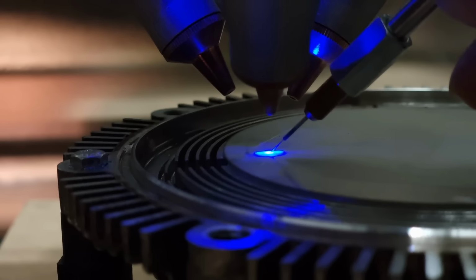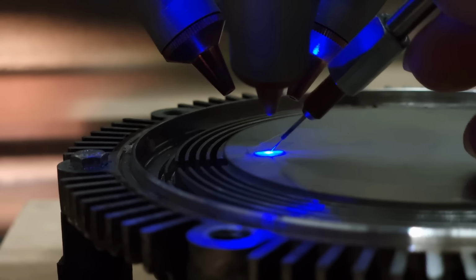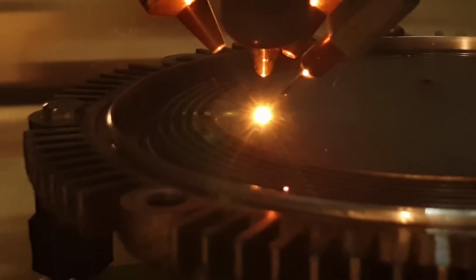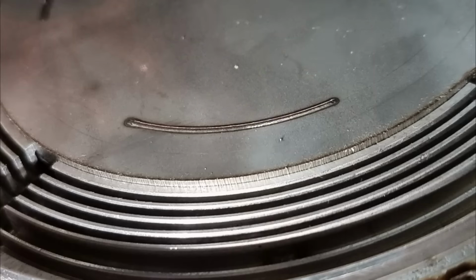Since I now had a rotating platform, I couldn't help but wonder what this process could achieve in an ideal scenario, that being an uninterrupted deposition relying on 2 lasers rather than 3. Now I did try 3 lasers momentarily, but without a coaxial feed that went about as expected, but with 2 lasers however, the reflections were much easier to manage. After the obligatory printing of segments, checking that I could translate a Cartesian scale to a rotational one, I tried putting down a few rings to gain a better sense of the deposition height.